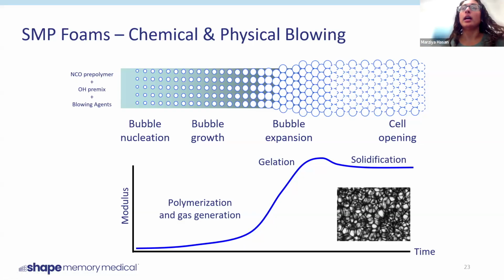Eventually, it'll get to a stable region where all of the polyurethane reactions have taken place. And as there's gas escaping the pores, we start to see some cell opening. And then what we end up with is just a completely solid foam, a thermoset material in our case, that is stable at that point.